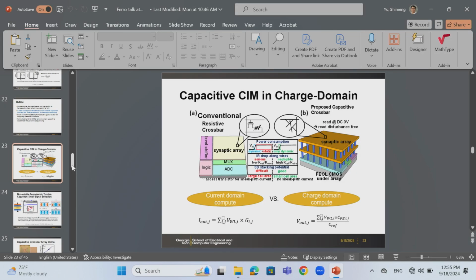So in the capacitive crossbar array, we don't think the sneak path is significant because in the DC mode, you do not have the leakage path, right? What is challenging actually is the disturb, because we still have the half select issue. When you program the selected cell, some of the cells will see half of the programming voltage. So we still think that half voltage disturb will be a problem. But I don't see any significant leakage path through the unselected cells, because essentially they are open circuit.